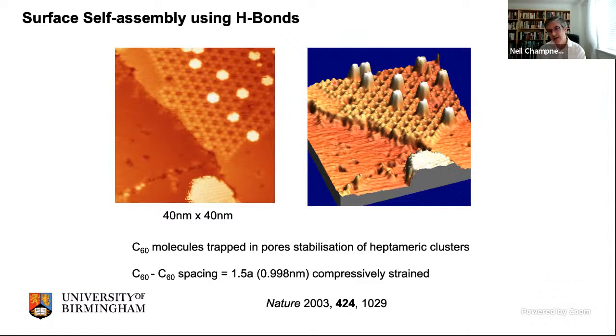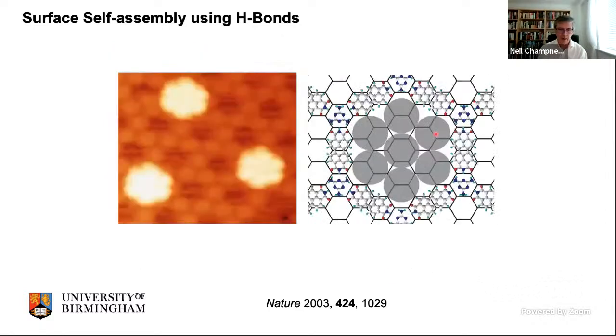So this is a 3-dimensional representation of this image. The image on the right is a representation of the image on the left. And the hydrogen bonded array is essentially like an egg box, right? And there are C60 molecules sitting within the pores. And if you look in more detail, you can actually see that there are 7 C60s all sitting in the pore at the same time. So there's 1 in the middle here, and then 6 around the outside.